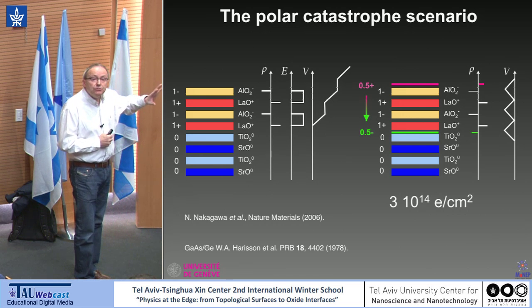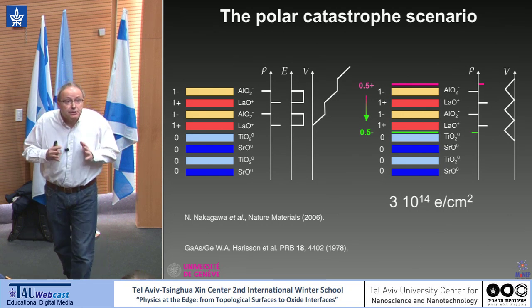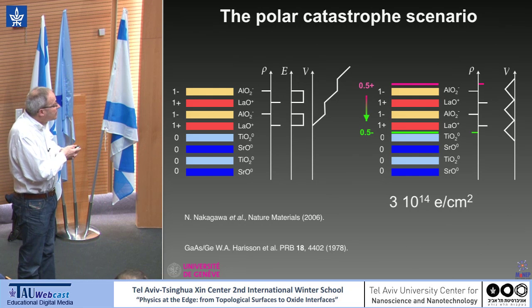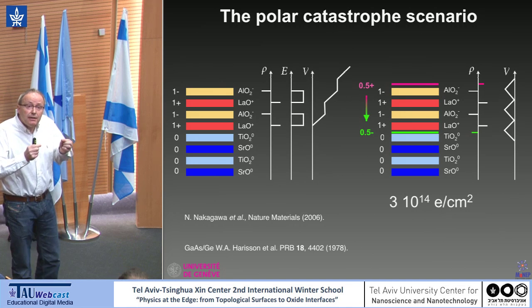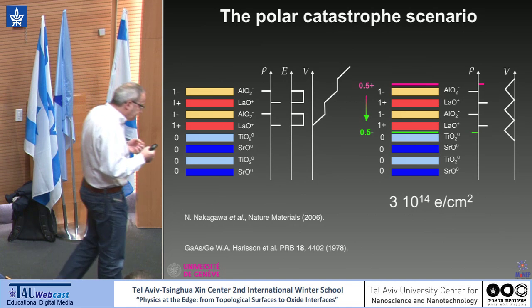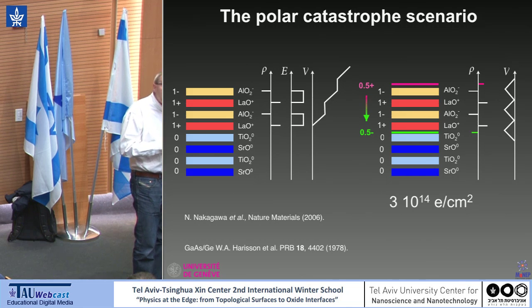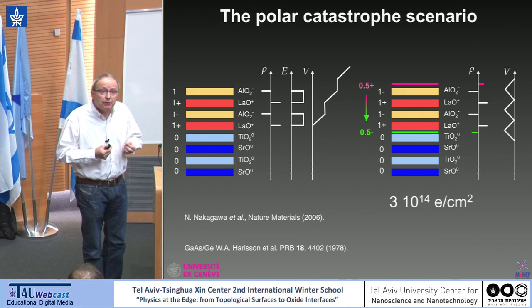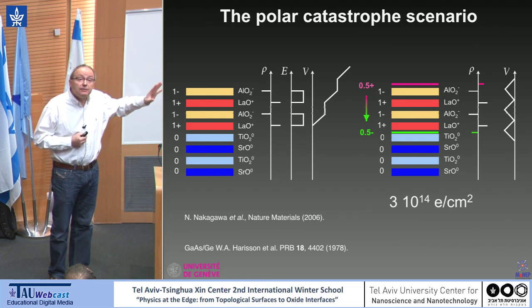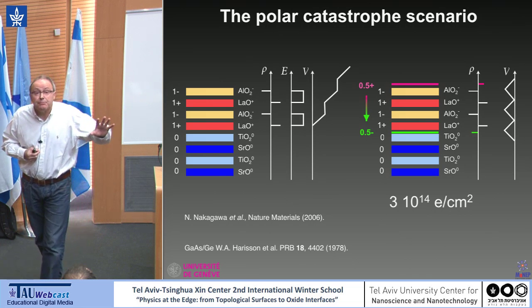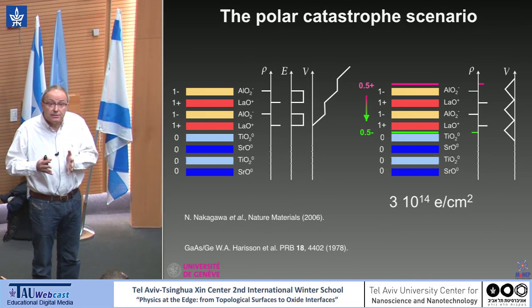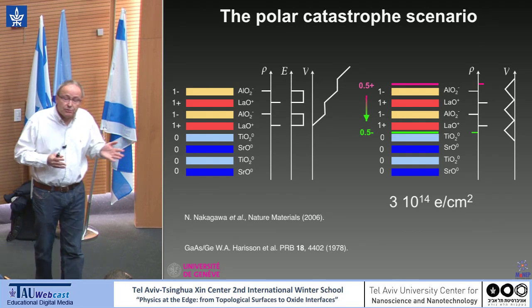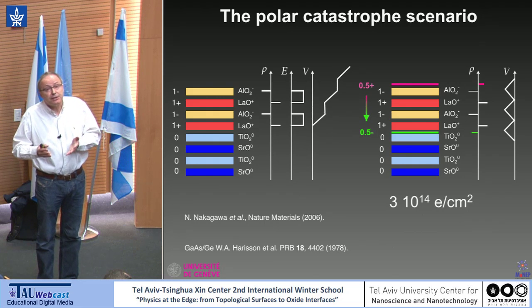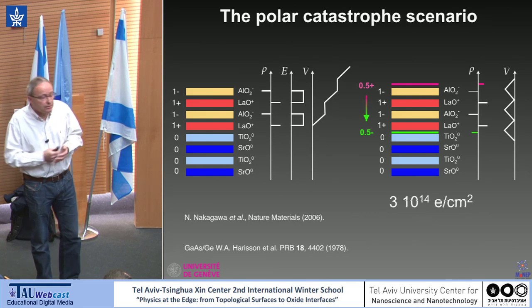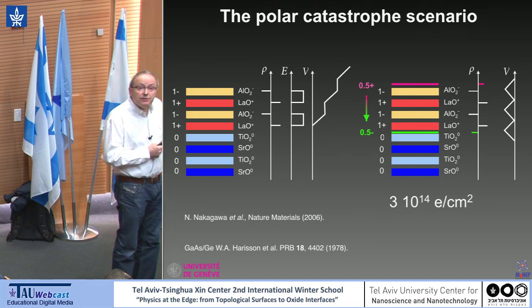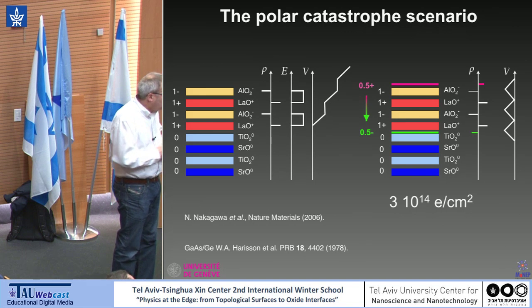This polar discontinuity problem is a well-known problem, and it happens in many systems, like in this gallium arsenide germanium system. But there, the system will work out an atomic reconstruction to avoid this diverging potential. What is different here is that titanium is a transition metal oxide, which can have different valences. In strontium titanate, titanium is 4+, that is d0, no electrons in the d band, but you can have electrons in the d band, and this is what happens when you transfer these charges.